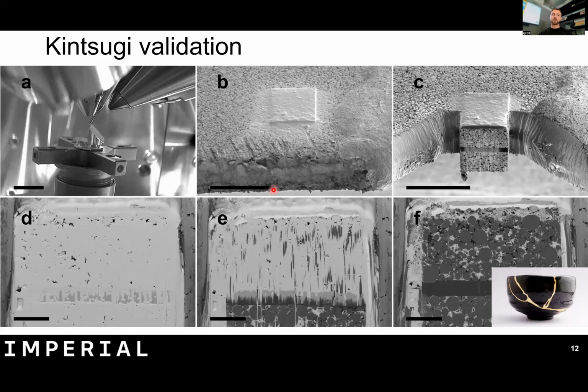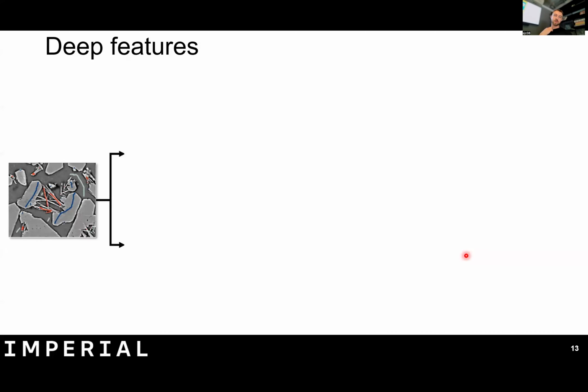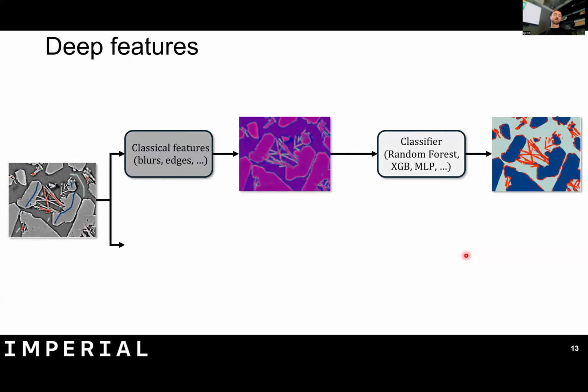Another nice approach for improving your imaging capability, we came up with a few years ago, called kintsugi imaging. In the top row, we see preparation of a sample as normal, but then we cover over the imaging plane with platinum and polish away the platinum again to get back to where we were. Now you can see that all the cracks have been filled in with platinum. This gives you a really strong contrast agent, essentially, and allows you to work out where the pores are in your segmentation.